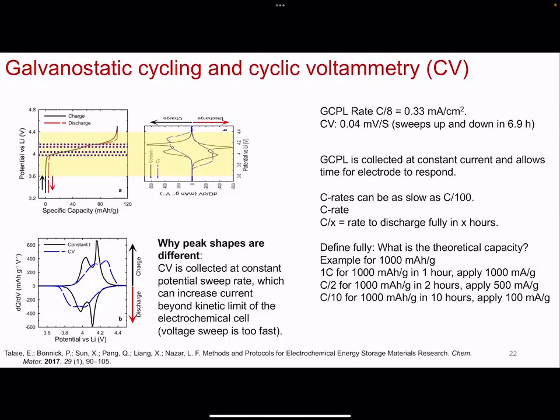And if you're trying to study a material within the confines of a particular region, like you don't want to cycle, not that lithium cobalt oxide is the latest and greatest. We moved on from lithium cobalt oxide a long time ago. But let's say you're working with lithium cobalt oxide and you never cycle to 272 milliamp hour per gram, right? You really want to study that x equals 0 to x equals 0.5 region. You cut everything in half. You can rescale your entire discussion and just say now 0.5 is my theoretical capacity.